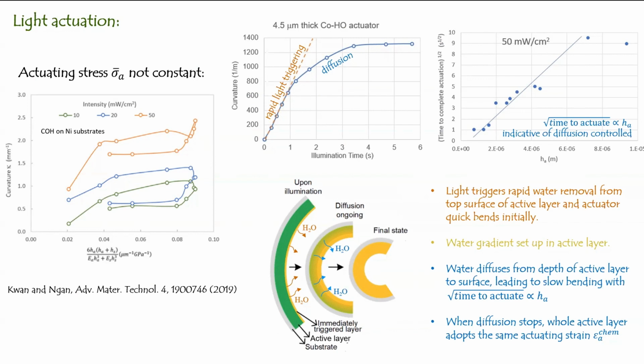So this is the actuator. The green is the active layer. You shine light from the right-hand side. The light can only trigger the very surface of the active layer initially. So that's this fast response. So that is quite instant, quite quick, right? And that's by removing water, as I said, from the turbostratic crystal structure.